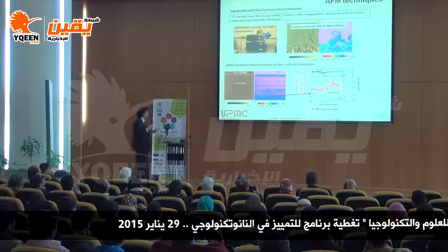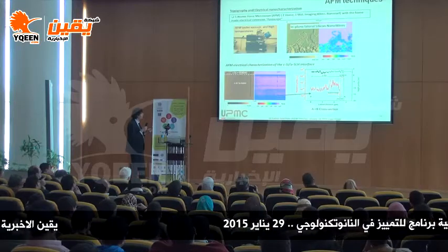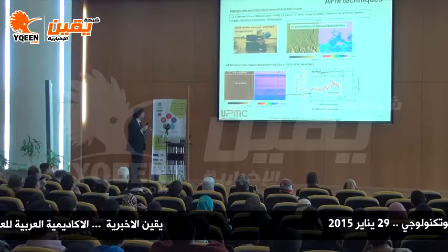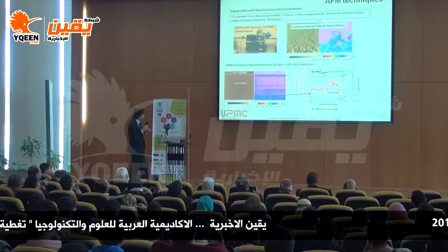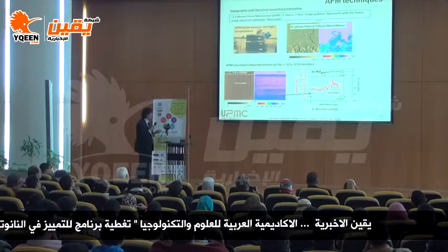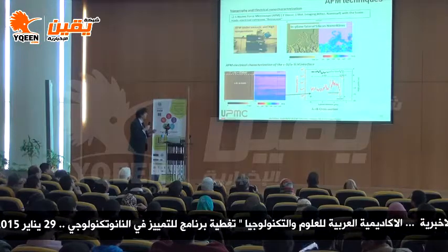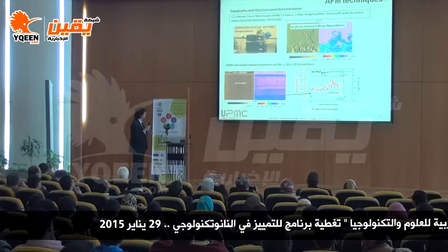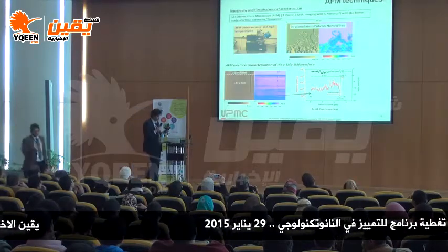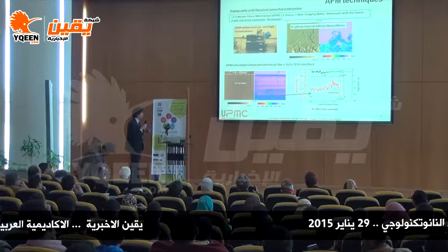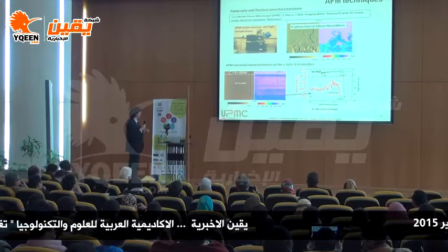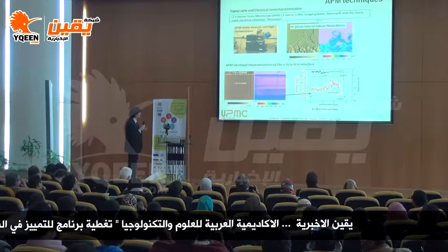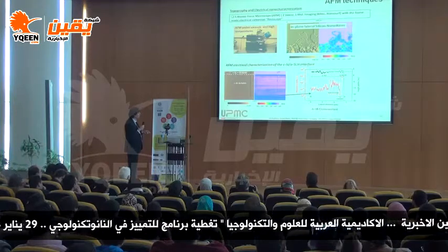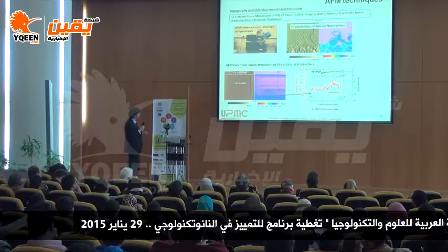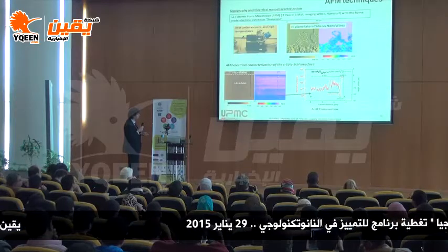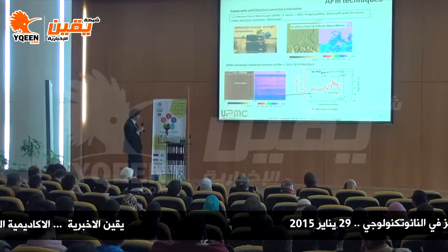Other tools that we own is the AFM, atomic force microscopy, to look at the topography of these nanostructures. So here we look at the topography of silicon nanowires, and we patented a dedicated conductive probe system that allows us to measure directly the resistance of such devices. So this is patented with Agilent. We call it the Resiscope, and the lab is right now running the Capascope to measure the capacitance at such a scale. So we can scan various heterostructures in the trench and look at where the transition between semiconductor 1 and semiconductor 2 is located, and also the space charge created by this heterojunction.